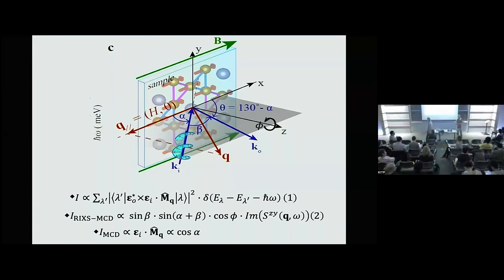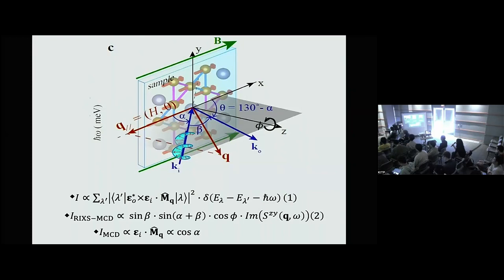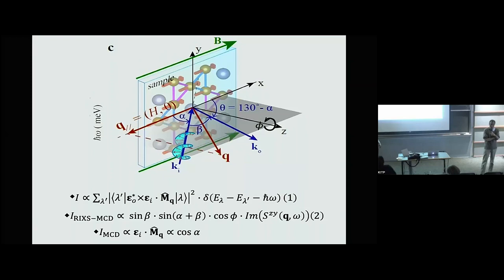We haven't done very detailed studies but my suspicion is it won't change things. The field we've got on the sample is needed for these measurements — remember you have to break the symmetry twice to see dichroism: you break it with the light and then at the sample. The analyzer integrates over both polarization states, so you always need a field. We've always had the sample in a basal-plane field, but I don't suspect there will be much happening.